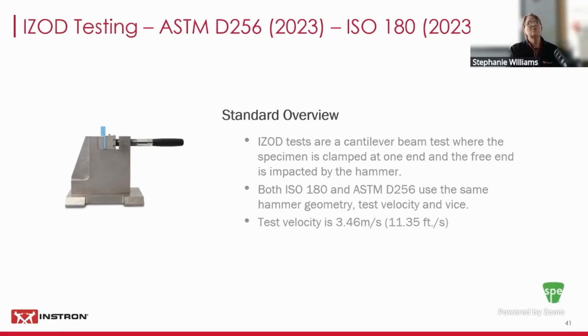Both standards use the same geometry to the striking face. Both test at 3.46 or 3.5 meters a second. Differences come in the sample size. ASTM is 60 millimeters long, same depth, 10 or 12, I mean, but then thickness can vary again from 3 to 12. ISO is, I believe, 80 millimeters long, 10 millimeters, and 4 millimeters. So they standardize as well on thickness and